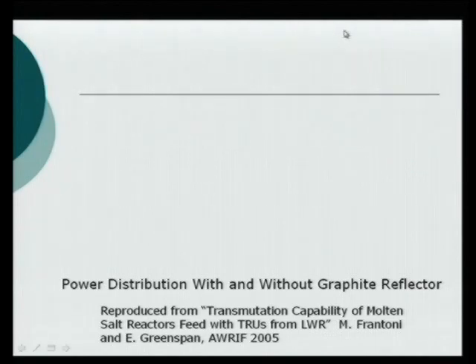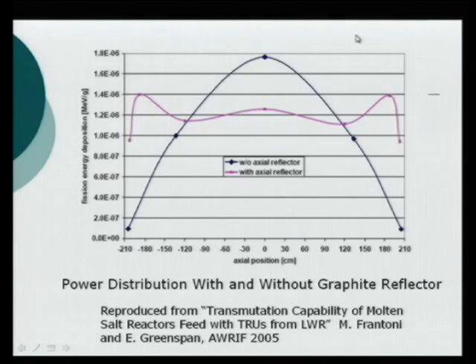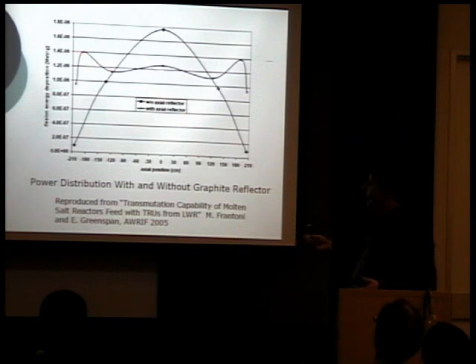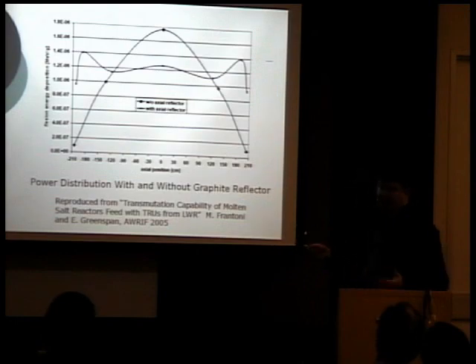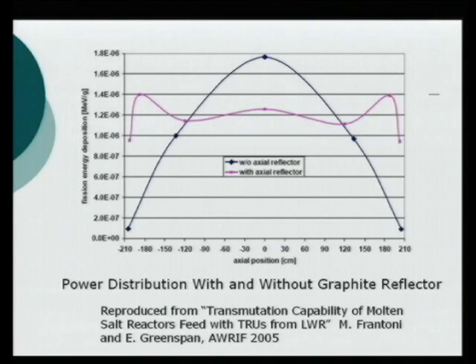graph here showing the power density with or without a reflector. If you don't have a reflector, the power density at your outer edge is really low, so hopefully the graphite could last a very long time. But as soon as you put the graphite in there, it reflects back the neutrons, it flattens out this power density, which is great if you have graphite in the core. We don't care about this if it's just a pure salt. But that makes a lot of power, so we have to have a thicker graphite, and you end up losing a lot of neutrons just in there.